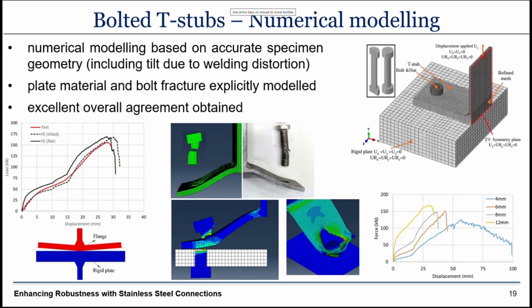So after doing the tests, numerical modeling was carried out, and the models were validated against results for both static and high loading rates for all the materials considered. We recently submitted a paper for the lean duplex stainless steel bolts, which is currently under review, and another paper on the two austenitic grades that we tested. Overall, we managed to obtain a good agreement between the experiments and the numerical modeling.